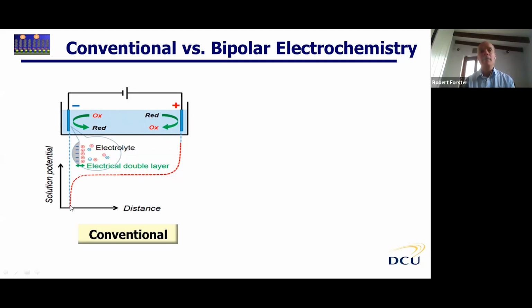We typically have a very high electrolyte concentration, and that causes the voltage that we apply to that working electrode to decay very rapidly into solution, so that if you were maybe 100 nanometers or so away from the electrode surface, there is in fact no electric field in that solution. The electric field collapses over the double layer structure very close to the electrode surface.